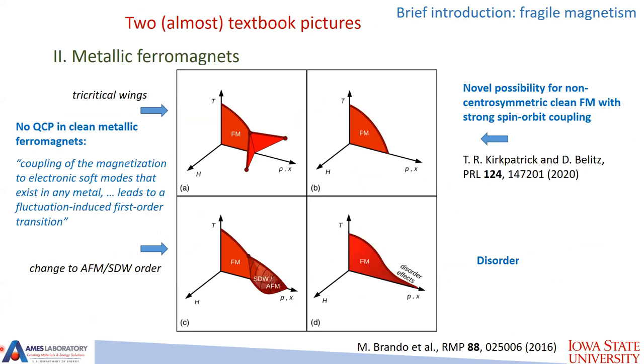Fine. There is a second textbook picture, the metallic ferromagnet. There is a theoretical statement that coupling of magnetization to electronic soft modes that exist in any metal leads to a fluctuation-induced first-order transition. So basically, the theoretical view, supported by many experimental sets of data, is that if you suppress magnetic ordering in a metallic ferromagnet, you can have one of four possibilities. In this one, you suppress ferromagnetic order, and then the transition becomes first order, and you can observe wing structures if you apply field in addition to pressure. Another option would be to go from ferromagnetism to antiferromagnetism, with its antiferromagnetic phase diagram when you apply field. Now, this option came to light actually rather recently for green materials.